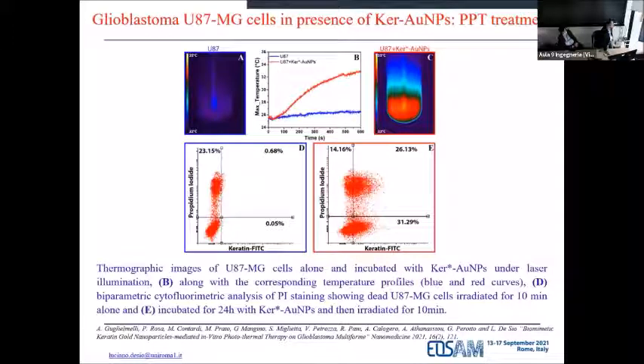As a result, you can see that, of course, we also run the control experiment, meaning cells without gold nanoparticles. You can see that without nanoparticles, there is no temperature increase. Conversely, in presence of gold nanoparticles, the temperature increase is about 6-7 degrees C. Now, you can say, okay, 6-7 degrees is not a lot. Don't forget that we run our experiments starting from room temperature. In real application, we don't start from room temperature. We start from 37 degrees C, which is the body temperature. So then 6-7 degrees is more than enough for killing cells. That's why we are happy about delta T.